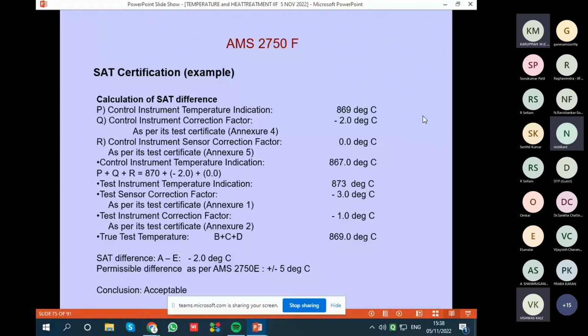I will not go into details, but I also make corrections for the calibration certificates. For example, a thermocouple, when it is calibrated outside, shows that there is a deviation -2 degrees. That means for my true temperature, I must add 2 degrees centigrade to the thermocouple reading. I do that. Similarly, my instrument has got a deviation, let us say -3 degrees. Then I must add 3 degrees so I get a true temperature. So I do all these corrections and get the final reading. Right in the beginning, I told you we want to measure the accurate and precise temperature. So by this way, we try to get accurate temperature as possible of the thermocouple and the instrument by making use of the certificates.